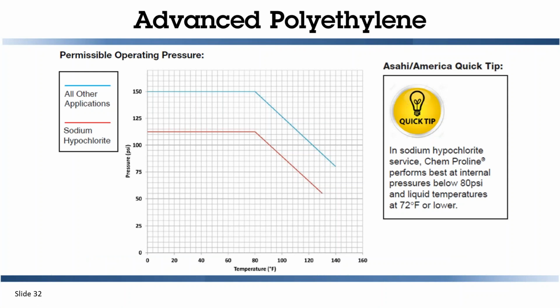For most polyethylene SDR11 applications, we have 150 PSI pressure rating. As temperature increases, we need to reduce that pressure. And so the maximum temperature is 140. We have a pressure limit of about 80 PSI. Because of this advanced resin, we're able to apply it to really aggressive media like bleach. We know that with the sodium hypochlorite and the advanced PE, we can have successful installations of about 110 PSI, 112 PSI at ambient temperature.